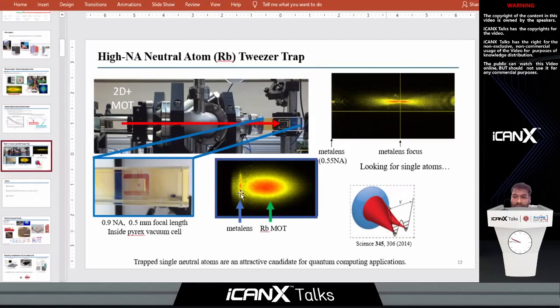And so the challenges for metasurface with this high numerical aperture optics, at least, would be how does one increase the field of view, if you would, of your metasurface. These are singlets, right? So the field of view, at least at this high numerical apertures, are quite limited. But if one goes to, say, a doublet approach, then maybe to say plus minus 25 degrees. But at least in this experiment that I showed you, we are really looking at trying to trap single atom just to see if we can even trap a single atom or not, right? But the challenge really would be to increase the field of view of these metasurfaces based lens.